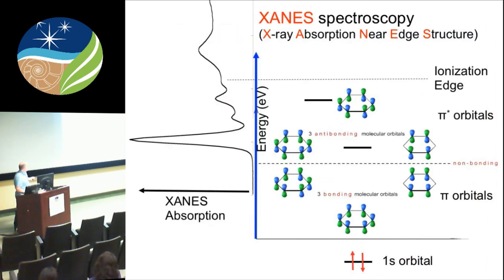So for example, in this cartoon, we're using benzene. If we photoexcite this poor little electron to 285 electron volts, plus or minus a couple, it'll find itself in one of the first unoccupied pi star orbitals, and you'll have a strong absorption band. So that's a signature of pi bonding, but you're looking at the antibonding states. And at slightly higher energy, 289 electron volts, you get to the second higher energy pi star. So that's a very simple approximation of what's going on. It's a little more complicated than that because this simple model doesn't explain that peak, or that peak, or that peak. But that's the core of it.